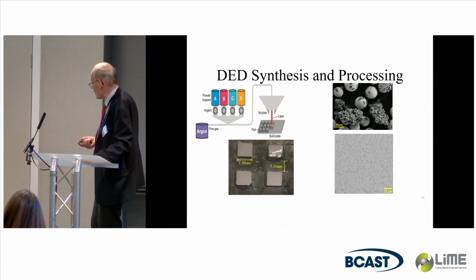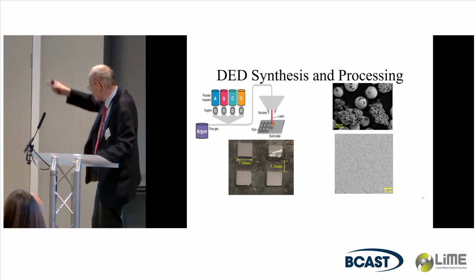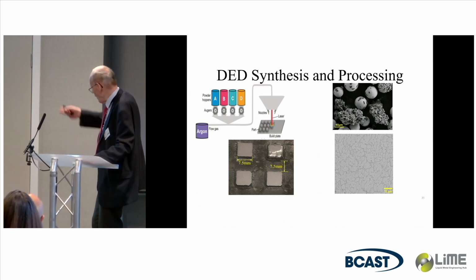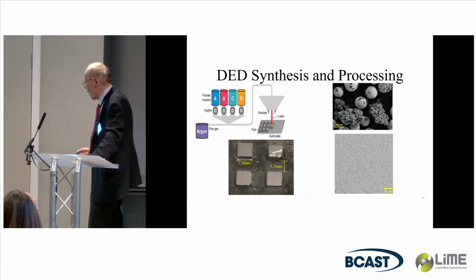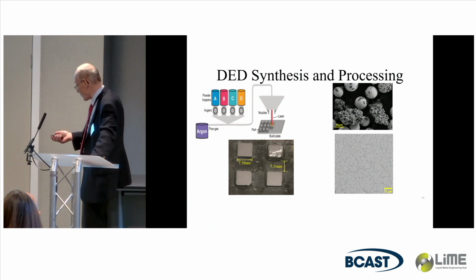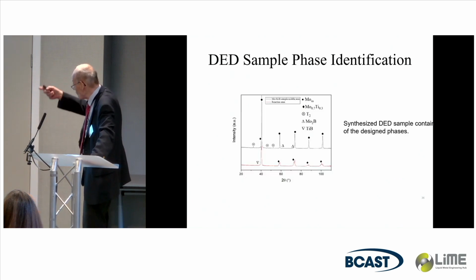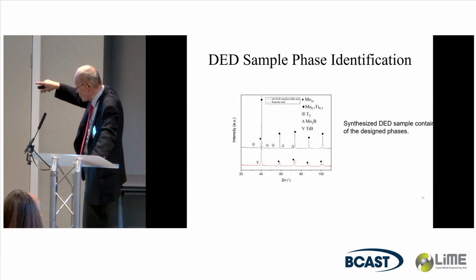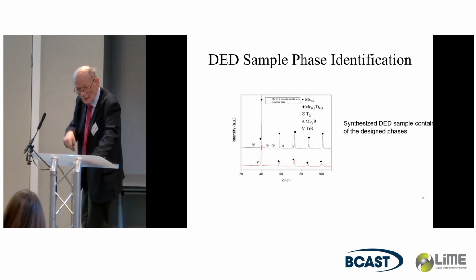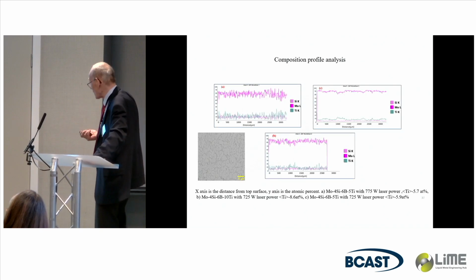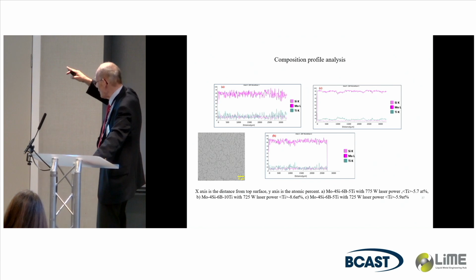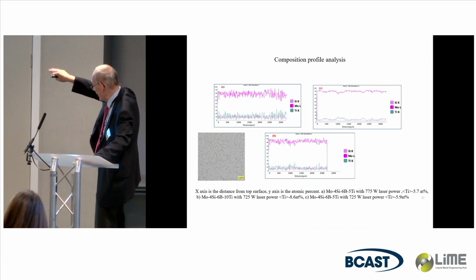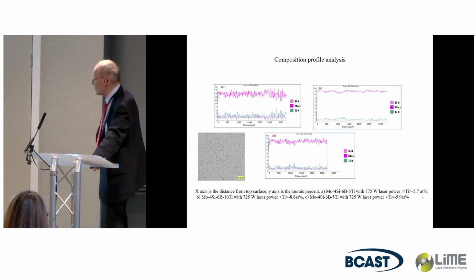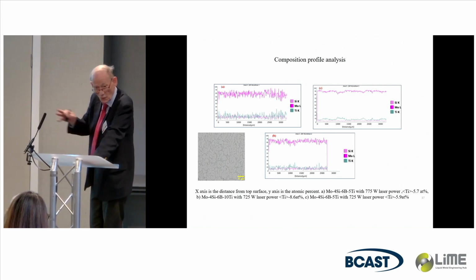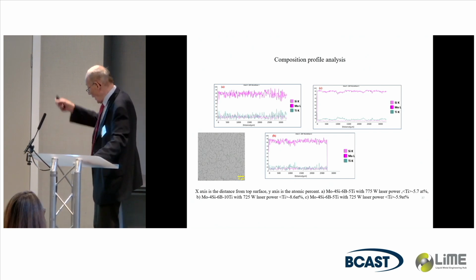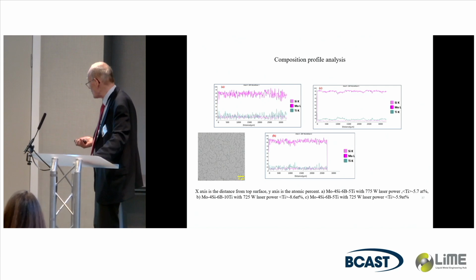And this is what we've done with directed energy deposition. There are hoppers. These are the feed stock, and we get a fairly uniform fine grain size. That's a 10 micron scale marker. We get the right phases. We get titanium boride at the build plate, and you can cut that away, so it's not a big problem. Compositional uniformity, we've added titanium as well, but over millimeters. These are thousands of microns. So the composition is uniform, and that's going from the bottom to the top on the build.